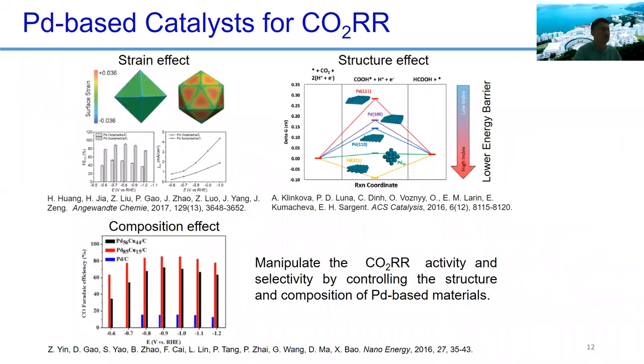So next, we're talking about the palladium-based catalyst for carbon dioxide reduction. And palladium is a very popular metal, okay, like palladium, like platinum. Okay, so it has been applied in many reactions. But in the carbon dioxide reduction, it was found that it can produce a lot of different products. And by engineering the structure and the surface, actually, the selectivity of the products also can be tuned. Okay, for example, if you make different kinds of nanoparticles to create a strain. So basically, usually you create a tensile strain because the adsorption of the carbon dioxide is too weak, you need to make it stronger.